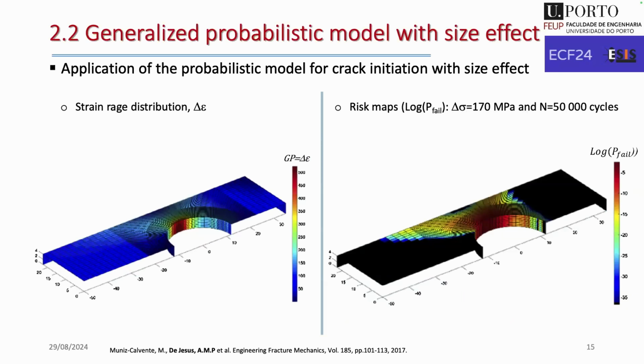With this model, for example, we can evaluate, starting with the fatigue parameter, in this case a very simple strain range distribution over the surface of the riveted plate. We can, for example, get the risk maps for the plate: for any given stress range and a given number of cycles, what will be the risk of failure of this component after this history.